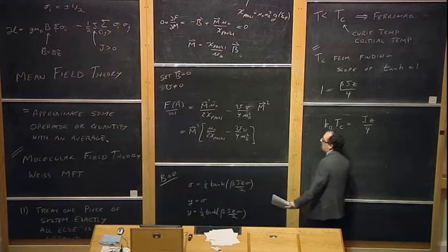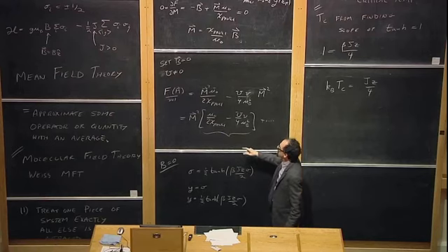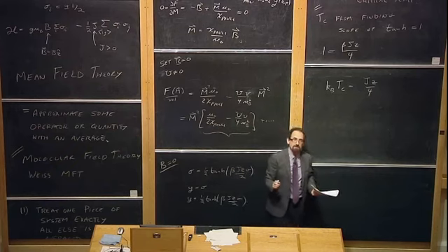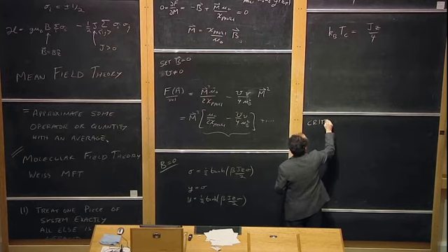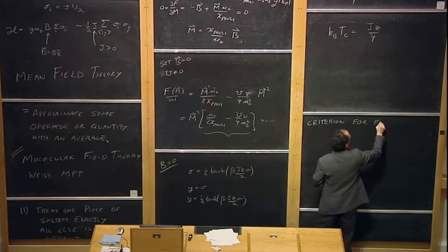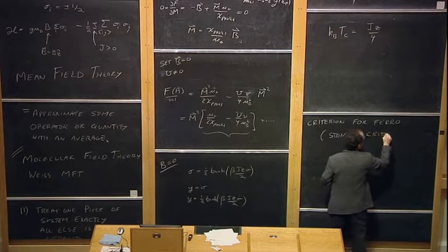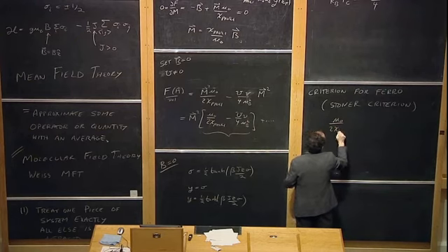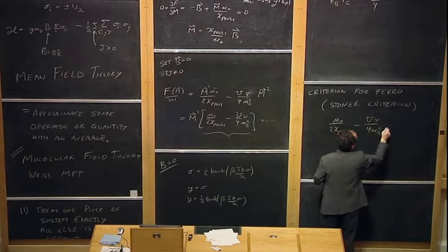And there will be higher terms too, terms which are quartic in magnetization and so forth, which we're not interested in. But the key thing to realize here is if this thing in the brackets is less than 0, then the magnetization wants to be non-zero. Whereas if the thing in the brackets is greater than 0, then the magnetization wants to be 0. Okay? So the criterion for ferromagnetism, which is known as the Stoner criterion, is that this mu naught over 2 chi Pauli minus U volume of the unit cell over 4 Bohr magneton squared should be less than 0.